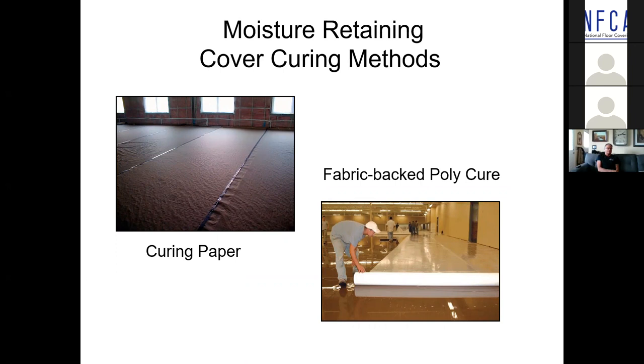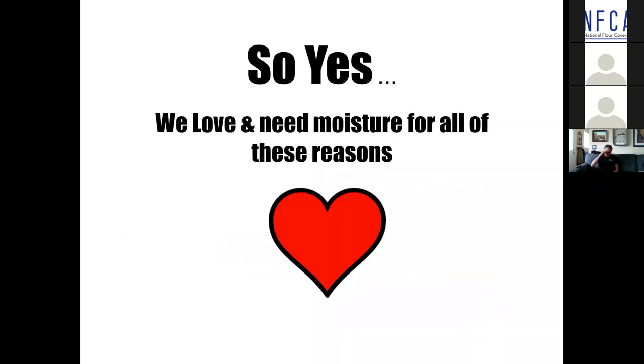It's a composite material of a fabric and poly where we just wet the underside of the fabric, dampen the surface. You're not continually adding water. It's a one-time thing, and it works very, very nicely. And the newer materials are lay flat. Not that it's necessarily important for a floor that's going to get covered, but if you have a bare concrete floor and you use regular poly with wrinkles and all of that, you end up with a negative mottled appearance on the slab, which is very undesirable, and you can't get rid of it. So these new materials are lay flat materials, not again that aesthetics are important because we're going to cover it. So yes, we love and we need moisture for every one of those reasons.